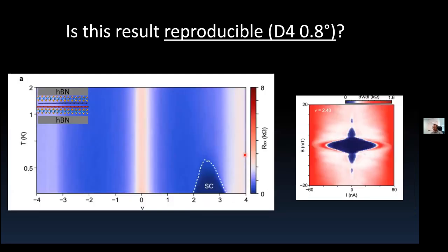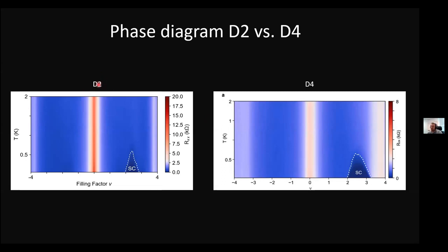And what also is important to verify is the temperature dependence, where you can see the Fraunhofer pattern. This one maybe looks even better than the previous one. But if you compare this result that I showed you in the device with 0.79 and this D4, which has all these regions here, the phase diagrams are exactly the same. So the superconductivity appears in the same places, and it's always near the half filling, and the Tc is also almost the same. It's a little bit less than a Kelvin, so something about 800 millikelvin.